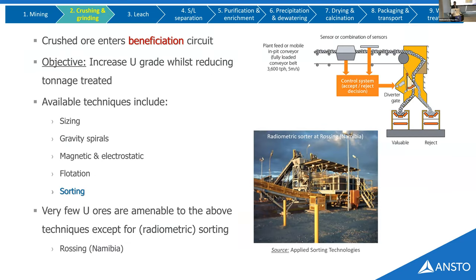One of the things that can be done, in order to reduce the amount of material that goes downstream, is looking at beneficiation. So that's the objective here, to increase the grade and reduce the tonnage. Beneficiation techniques, there's various ones around. You can use gravity, sizing, magnetic, electrostatic. Flotation is one of the ones that's commonly used in mineral processing for making base metal concentrates. Sorting is another one. Very few of those techniques actually work for uranium, except for, funnily enough, radiometric sorting, because it's radioactive. So it has been applied at Rossing in Namibia.